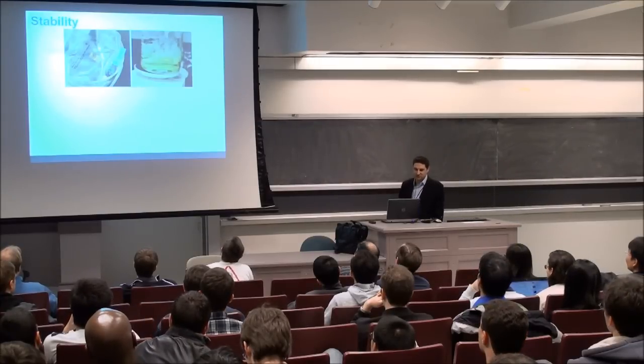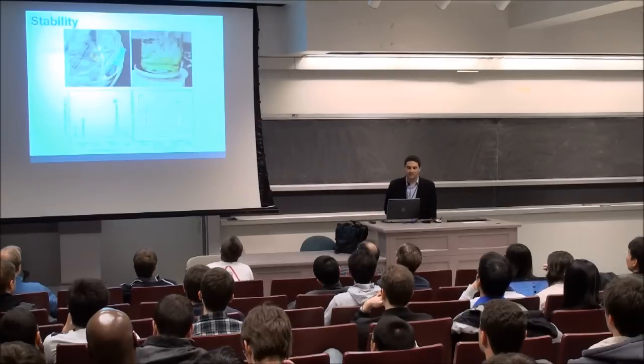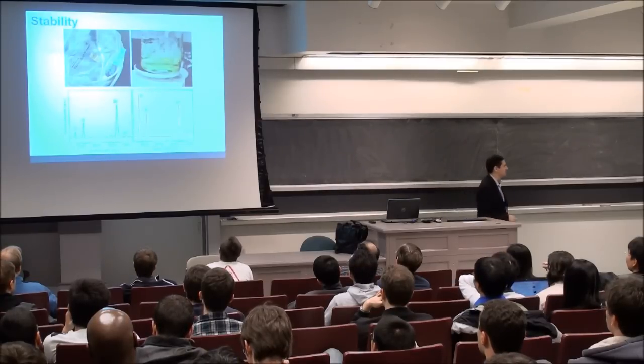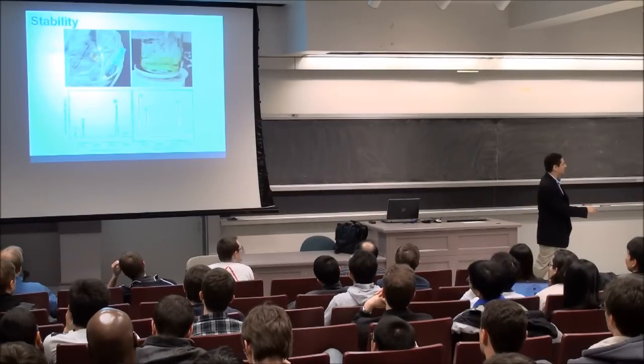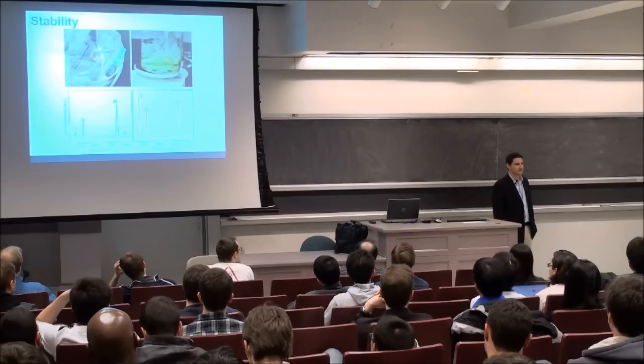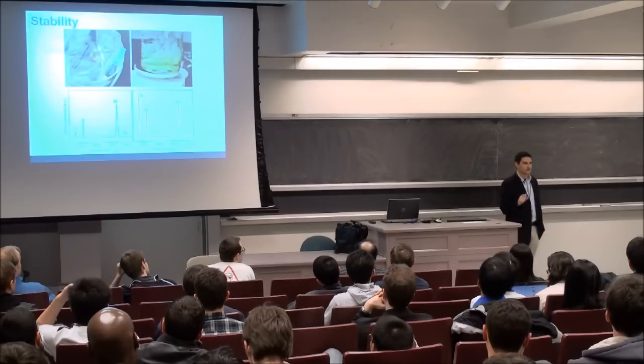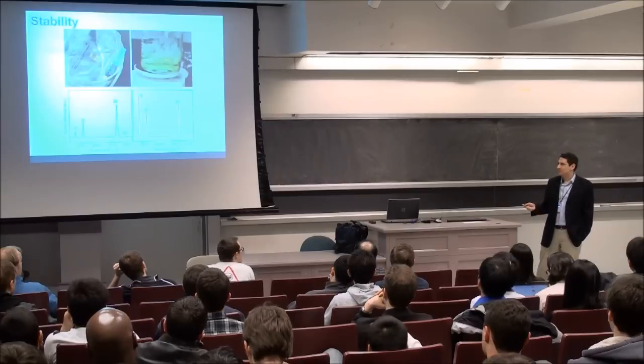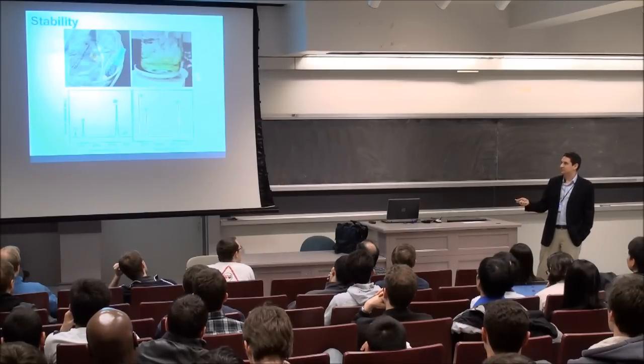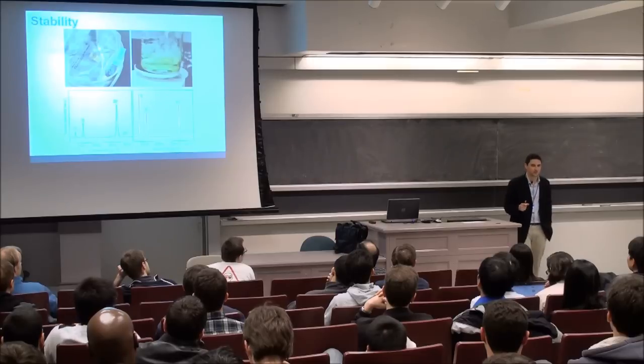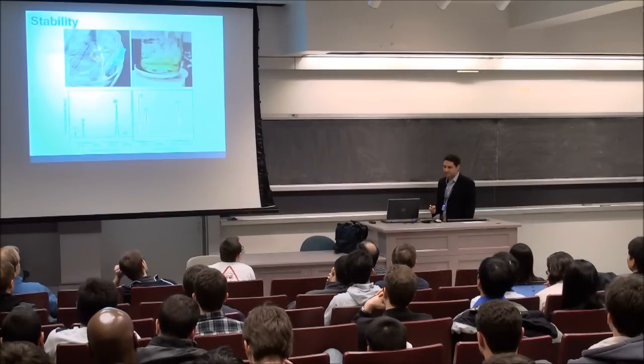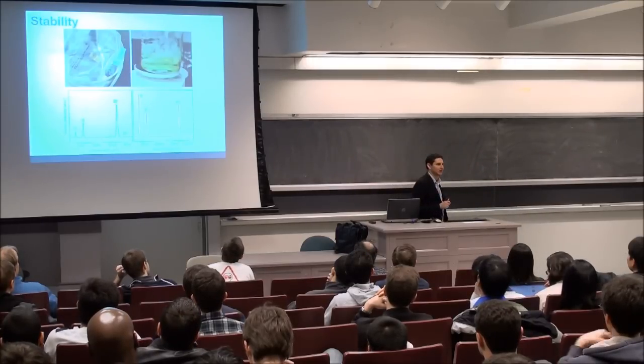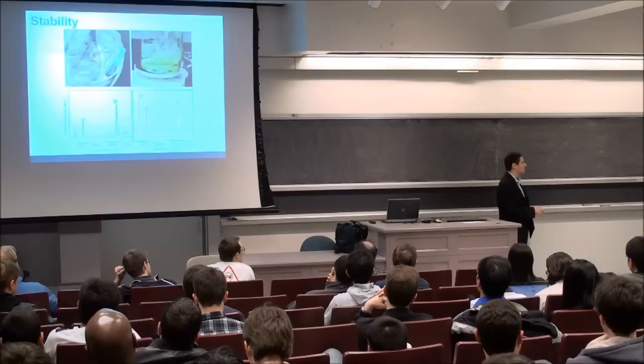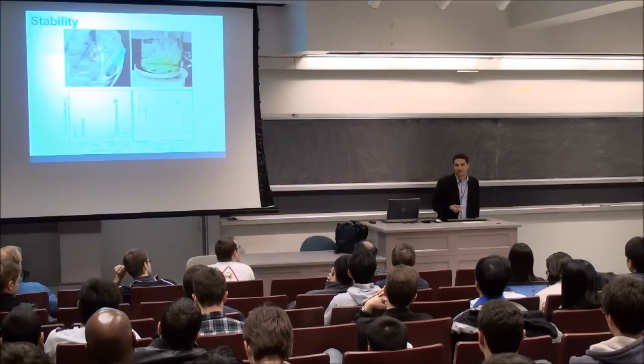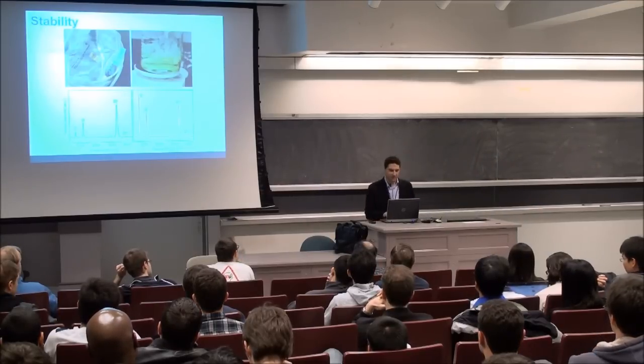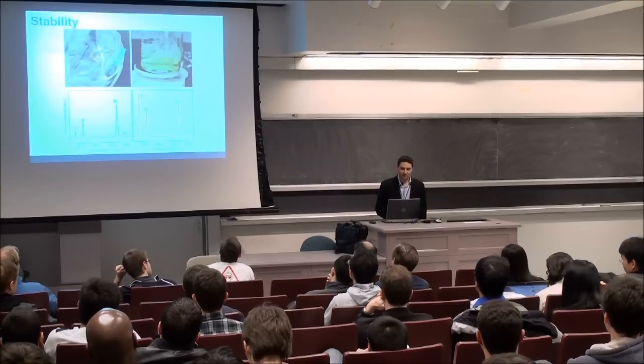If you take it out and then do the Raman spectrum after that, you do see that there's an increase in the D peak here on the graphene. And part of the reason for that is that the D peak actually represents graphene edges. So we are probably creating more graphene edges, not through this process, but through the sonication process. So there probably are some more defects here, although that may not necessarily be a bad thing in graphene because it's a semi-metal. So it may be a way of opening up a band gap in the graphene.